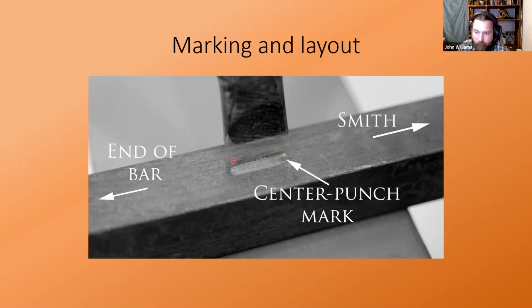So by the time you measure to end of stock from this side, again, that was 2 5/8. You have your 7/8 inch punch. You subtract that, you end up with about 1 inch and 3/4 to the end of the bar. This is just so that you get the appropriate weight and proportions. It's a little important to make sure that you do your layout well from the start.